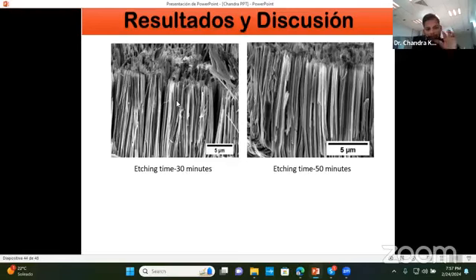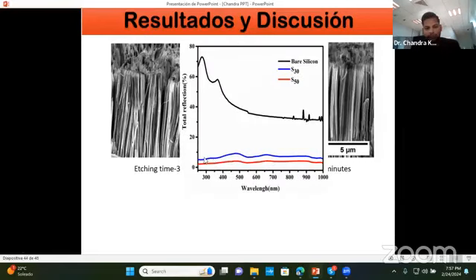If you use this nanowire for a silicon solar cell instead of plain silicon or textured silicon, you will get a more effective outcome. See the reflection. In the case of silicon nanowire, which I reported also in Optical Materials earlier, it is around 6 to 7% as compared to polysilicon. That is quite effective and useful for such devices. If we are fabricating advanced devices, then for light absorbing, I didn't add here the data that I calculated from FDTD, a theoretical software. The light trapping behavior is quite effective.